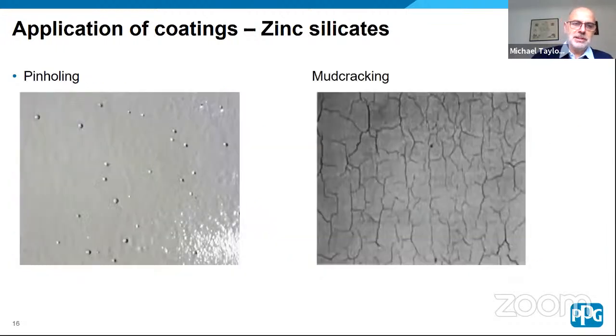And just to show you what pinholing looks like, on the left hand side of the screen, you can see the little bubbles. You don't tend to see these in the silicate itself, and you may not see them in the intermediate, but where you'll definitely see them is if you put a glossy top coat on. They're hard to repair, and once you've got an area like this, really you need to go right back to the silicate to repair them. And on the right hand side of the screen, you'll see the mud cracking you can get if you over apply zinc silicate to higher film thickness.